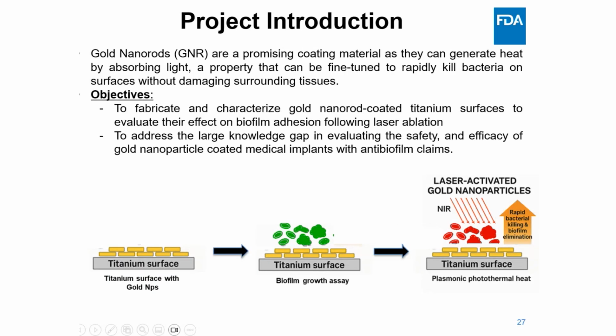So let's talk about project number 2. Here we are developing titanium surfaces coated with gold nanorods to target Staphylococcus aureus biofilms using photothermal laser ablation, while also assessing the biocompatibility of these functionalized surfaces using mammalian cell lines. In this project, we are developing gold nanorod-coated titanium surfaces to combat bacterial biofilms on medical devices. As some of you know, gold nanorods are promising coating materials as they can generate heat by absorbing light, and we can fine-tune this property to rapidly kill bacteria on the surface without damaging the surrounding tissues.